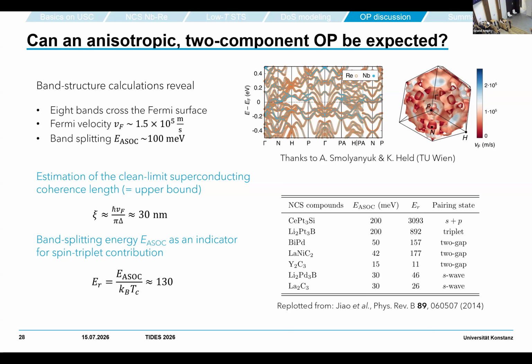If you look in the literature, this cerium platinum silicide (CePt3Si) is well known as being a triplet superconductor. It has a much larger ER, 3000. Lithium is also discussed, has 900. And for these ones, bismuth, palladium, lanthanum, nickel...